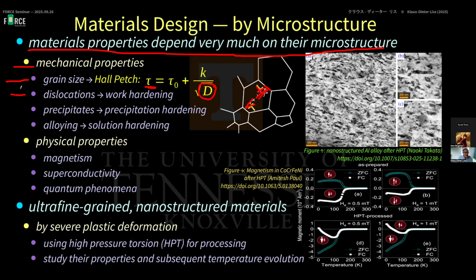So we also have dislocations already. They give you further work hardening because dislocations can be entangled with each other. Precipitates lead to precipitation hardening, and this is because precipitates hinder the free movement of dislocations. And we have solution hardening. That's where a cloud of solutes is around a dislocation, for example, also pinning the dislocation down.